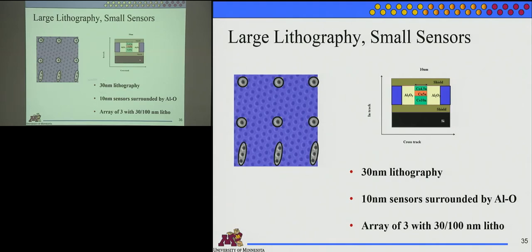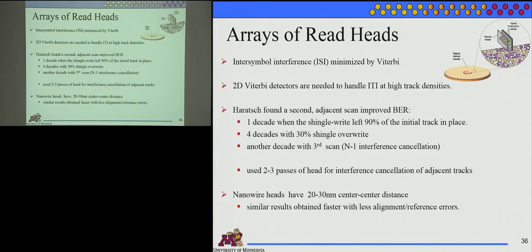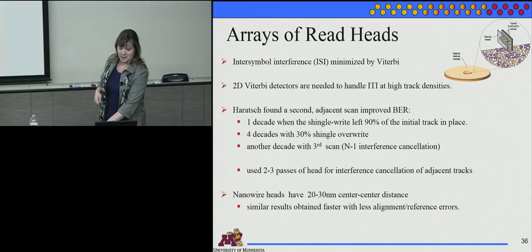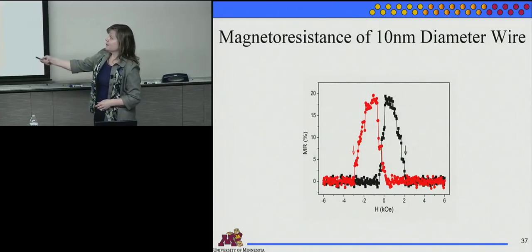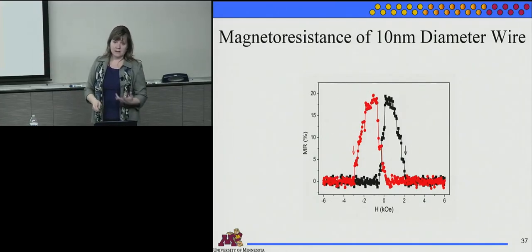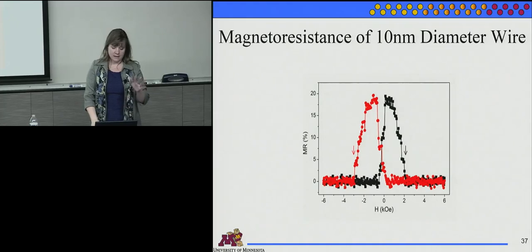30 nanometer diameter gives you 10 nanometer structure already surrounded. And if you want to do something even easier, make a 100 nanometer blob by 30 nanometers, and you'll have 3 10 nanometer devices already in aluminum oxide, so an array of read heads ready to go. This is sort of explaining why you might want an array, and I'll skip over that. Here's the actual magnetoresistance of a single nanowire, 18-ish%. See, there's some noise there in the magnetoresistance.